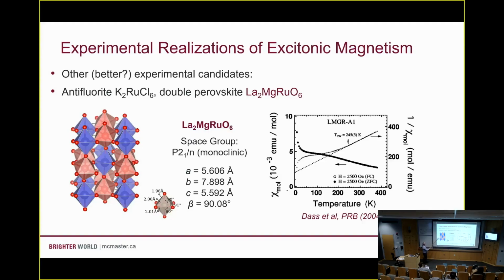This is a closer look at the crystal structure. So we've got ruthenium here at the center of an oxygen octahedra. You can see that these are corner-sharing octahedra, but you've got non-magnetic magnesium octahedra here as the nearest neighbors. Okay, so these are pretty well-separated octahedra here. There is a little bit of an axial distortion here. So two of these ruthenium-oxygen bond lengths are a little shorter than the others. You can imagine the octahedra sort of squished.